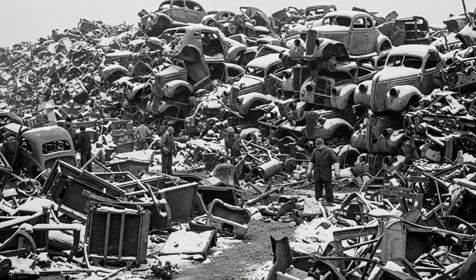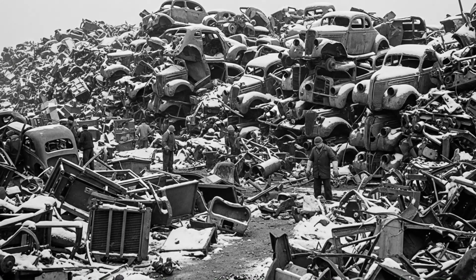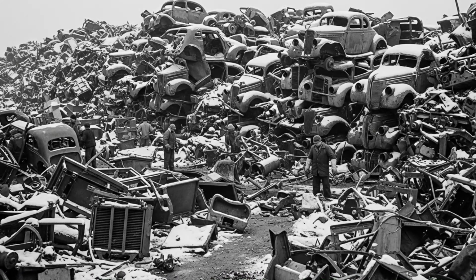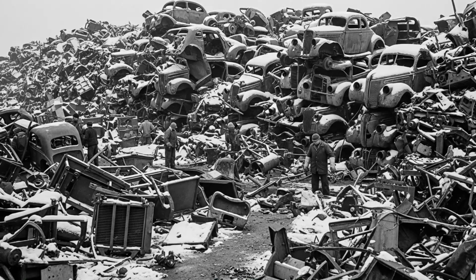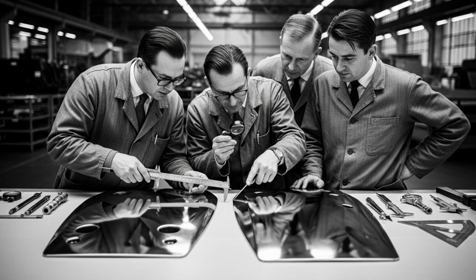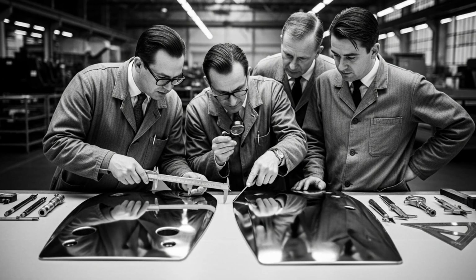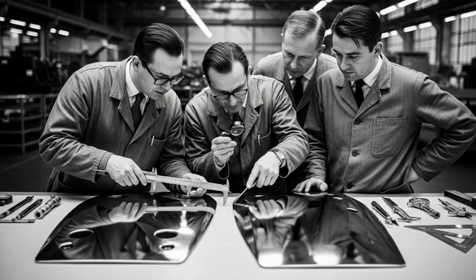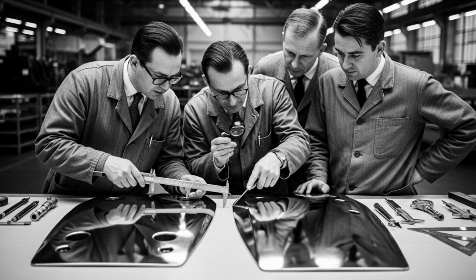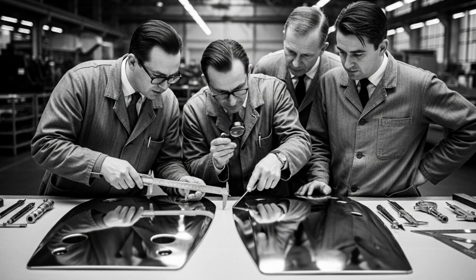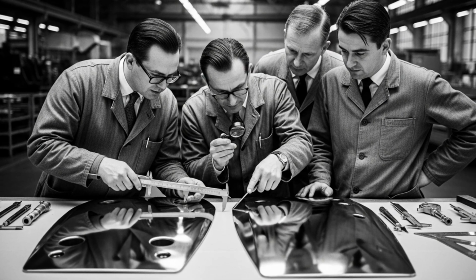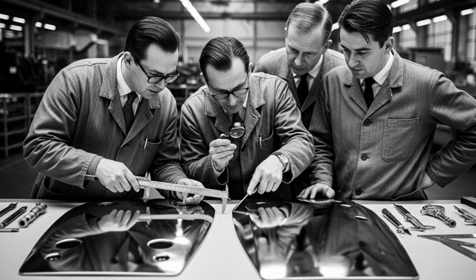Each change was justified by engineers who assured Speer that the degradation was minimal, that the tanks would still perform adequately, and in testing, under controlled conditions, they did. But testing was not war. War was a tank taking a hit from a Soviet 85mm gun at close range. The shell striking not the thickest part of the glacis, but the weld seam where two plates met.